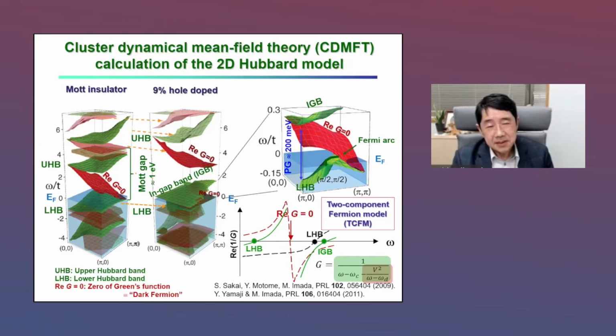Yeah, this is a kind of spin fluctuation because four-site cluster DMFT means a four-site cluster in which spin correlation between neighboring spins is strongly antiferromagnetically correlated, and the low energy spin fluctuation, which is directly responsible for superconductivity, is not very clear from this calculation because the cluster is small, but it successfully explained the high energy part of the pseudogap, I think.